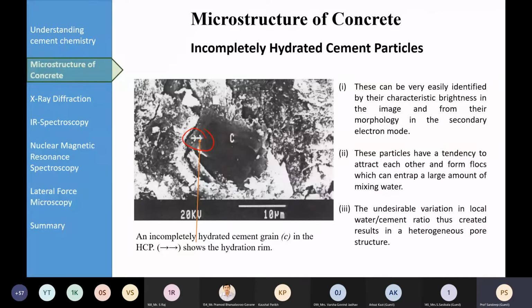And so the takeaway from this slide is that if you are seeing a microstructure image of a concrete sample, and you are seeing certain characteristic bright images there, then you should be very cautious. That is telling us that the hydration has not taken place completely, and there are still incompletely hydrated cement particles, and they are going to even change the water cement ratio. That is the variation in water cement ratio across the matrix, which is not desirable from any point of view.